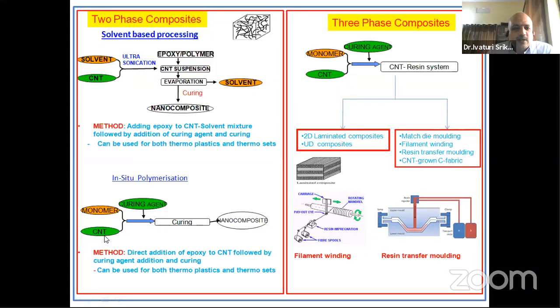The other method is you add the CNTs in the monomer of the polymer, add the crosslinker, and then allow it to cure. So you get a nanocomposite. Basically, add CNTs to the polymer matrix of monomer and a curing agent and cure it. Many people have reported improvements of the order of 100%, 150% by adding this. But the problem is there is no use of adding the CNTs in a pure resin system, because the pure resin system strength is of the order of around 100 MPa. So by adding this, you may get 200 MPa.